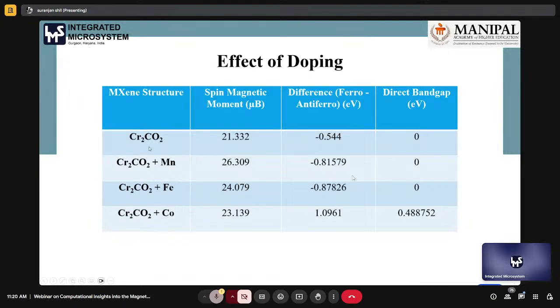So what we can see from here is that if we dope another metal into this chromium carbide with oxygen termination, we get a change in magnetic moments, and also we see the ferromagnetic to antiferromagnetic change. That means chromium carbide with oxygen termination is ferromagnetic, but if we dope with cobalt, we got the antiferromagnetic behavior. We can switch the magnetic properties by doping. But for manganese and iron, we can increase the magnetic moment, but the magnetic behavior remains the same.